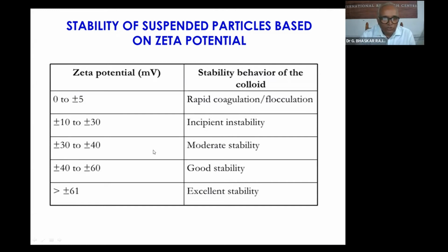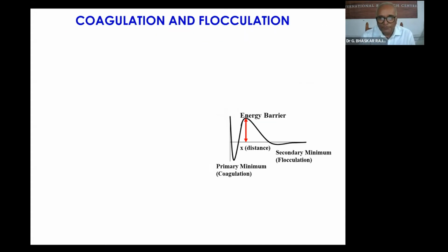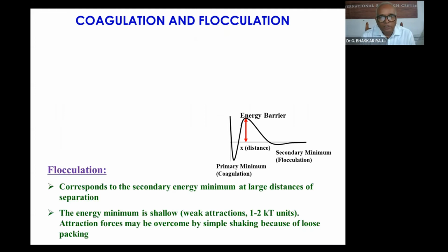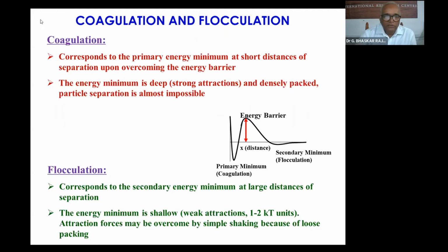So this is the extent of zeta potential we need to develop on the surface of these particles. We can manipulate this zeta potential, to get the required value, by manipulating either the pH or the adsorption of some reagents on top of that. Then, coagulation and flocculation: this knowledge also we can use.